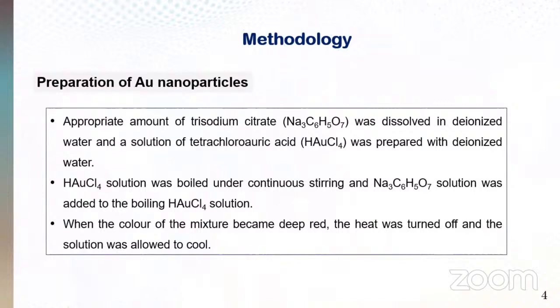Methodology. In order to prepare gold nanoparticle colloidal solution, first a 0.1 M trisodium citrate aqueous solution was prepared. 2 ml of the solution was added to 20 ml of 1 millimolar tetrachloroauric acid boiling under continuous stirring. When the color of the mixture becomes deep red, the heat was turned off and the solution was allowed to cool.